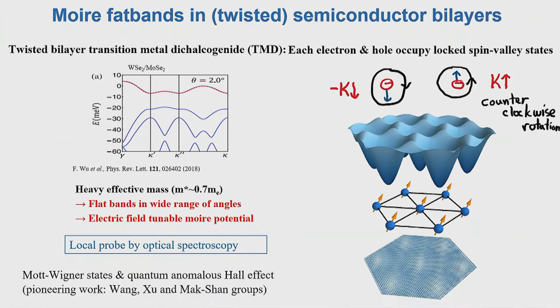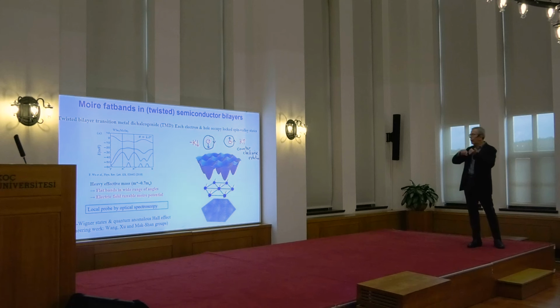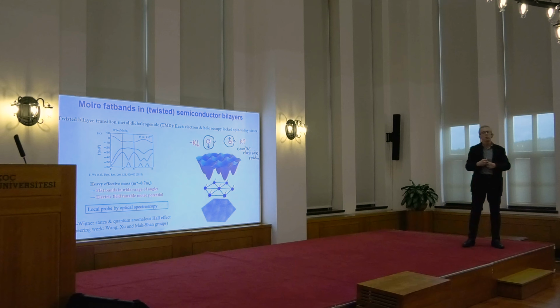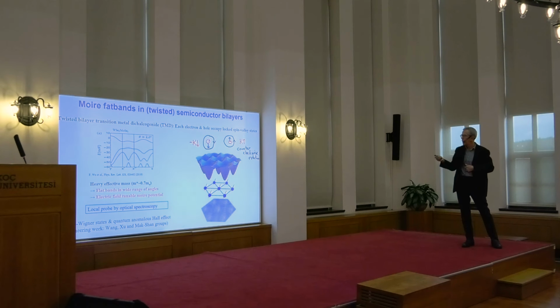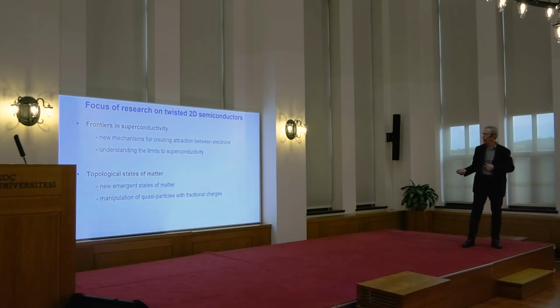And I should say that in this material system, normally we talk about electrons having spin up or spin down, could of course be any superposition. Here, the spin is tied to a degree of freedom, so-called valley. What valley tells us is that these electrons actually have a chiral motion. If they're spin up, that means that they also have an orbital angular momentum of, let's say, +1, and if they're spin down, then they have the opposite angular momentum. So whenever we say spin, that really means that the spin is tagged to this orbital angular momentum degree of freedom. Just mention that in case I'm going to use it.